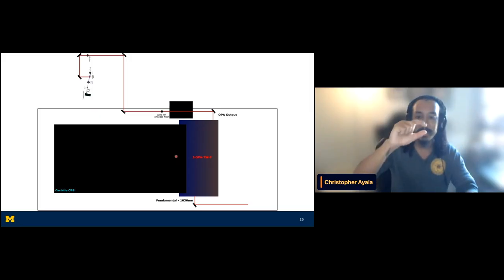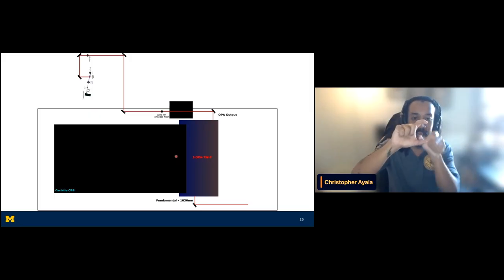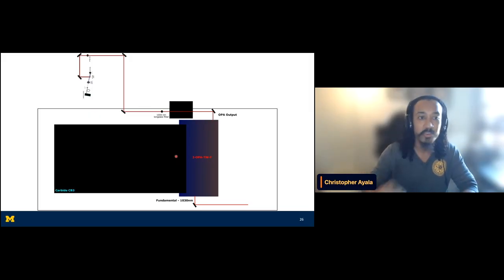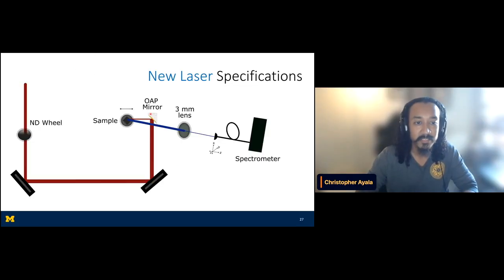So what that means is that the beam is wider in one direction than the other, and the issue with that is when you are looking at this focusing apparatus, the material wouldn't give you the highest peak intensity power onto the sample that we would hope to get. We're still able to clearly generate third to seventh order harmonics with high intensity, but we're thinking currently that this could be a limitation in even seeing that ninth order harmonic, and it would be an issue when going into vacuum and trying to find higher order harmonics, because we would not be able to produce the peak intensity to generate harmonics.